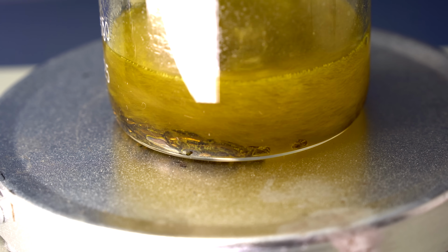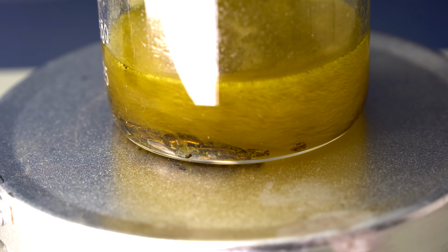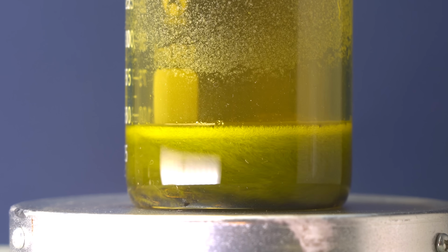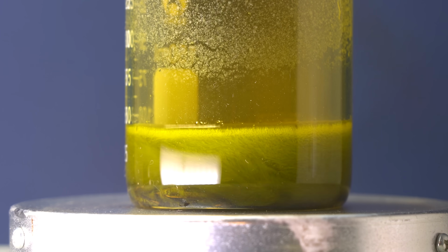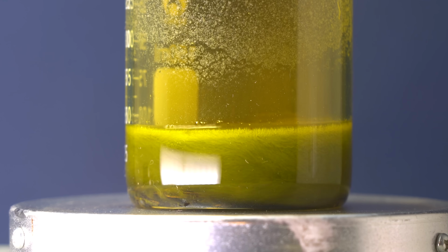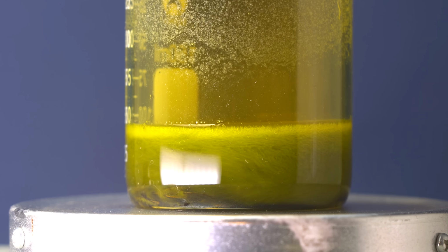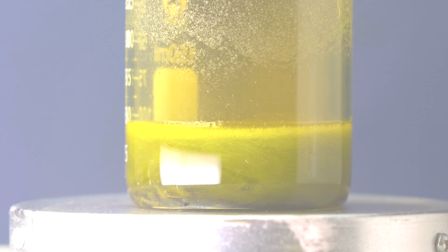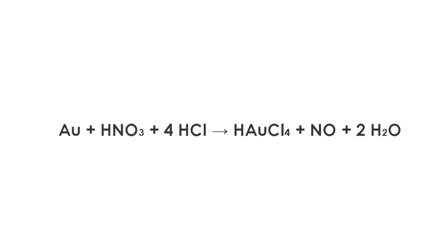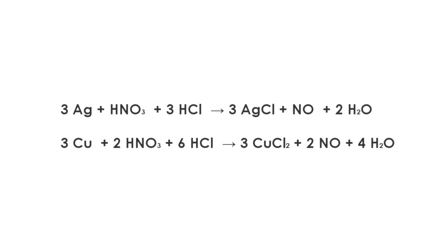When stirred, the process runs even faster, because the forming silver chloride is quickly removed from the surface of gold, preventing it from passivating the surface and stopping the reaction. From a chemistry point of view, under the influence of nitric and hydrochloric acids, gold is oxidized to chloroauric acid. Along with that, silver and copper present in the bracelet are also oxidized to copper chloride and silver chloride.